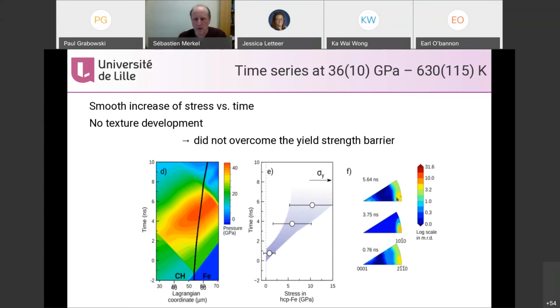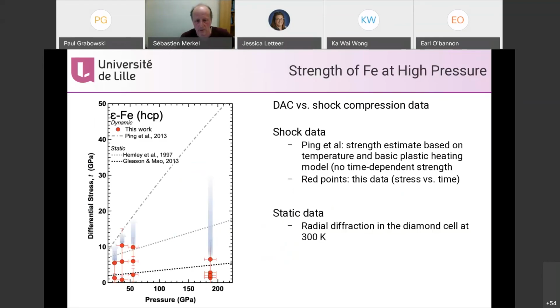When the stress goes up and doesn't get extra evolution, it confirms what I think: we get this peak, this elastic increase of stresses, and then once you have plastic flow, twinning, dislocations, whatever, you relax. So it asks us, what is the strength of iron under high pressure, under shock conditions, under static conditions? It's a summary figure of the strengths of iron that have been reported.